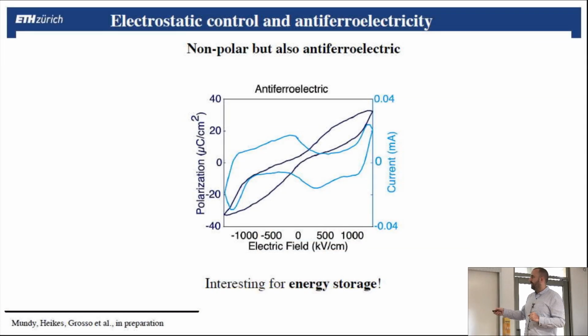Yeah, sorry. So here in light blue, you are seeing the current. And in dark blue, you are seeing the polarization. And where you can see that it's antiferroelectric or going to antiferroelectric is because here is shrinking, so going to a linear behavior. But also you see here two peaks for the current, which show inversion of the current, like up and then down. And this is also characteristic.